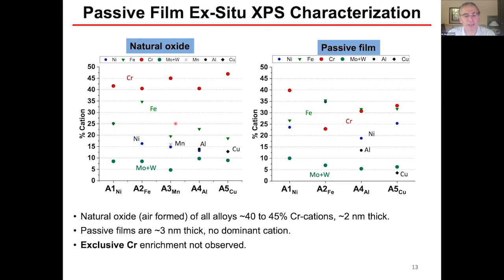And in fact, we see that there is chromium in the passive film. This is the natural air-formed oxide. Here's the passive film. So this air-formed oxide is rather enriched in chromium. The passive film is not exclusively chromium. All of these elements, iron and nickel, are participating in the passive film that's formed. And so I would say there is really no dominant cation in these different alloys.